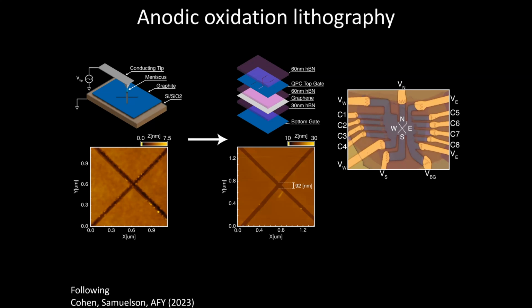So you take an atomic force microscope tip, which is coated in metal, in a damp environment like Santa Barbara. You bring this tip very close to the graphite, and then you pull it away a little bit, and a little water meniscus forms between the graphite and the metal. And then you put a voltage on that metal tip. And what happens inside this little meniscus, which is about the size of the AFM tip, so maybe 10, 20, 50 nanometers, is that you just electrochemically oxidize the graphite.